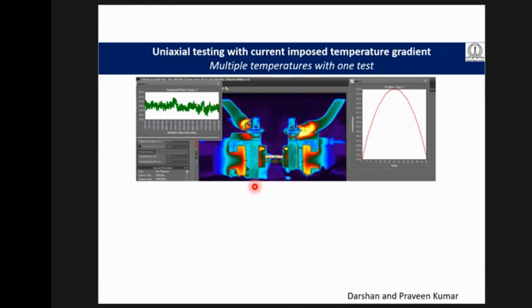Just continuing on this line with regard to high throughput testing. Well, high throughput is really a big basket. There's temperature, stress, and strain. So we've looked at strain and stress here so far. But here's an example of where you can get multiple creep curves from different temperatures. So here, the grips are heated by passing current through them, and the sample is in the middle. So if there's a small temperature gradient between the ends and the middle.